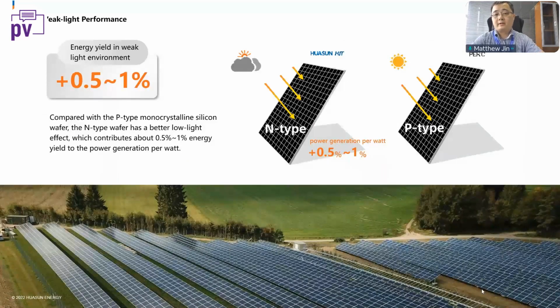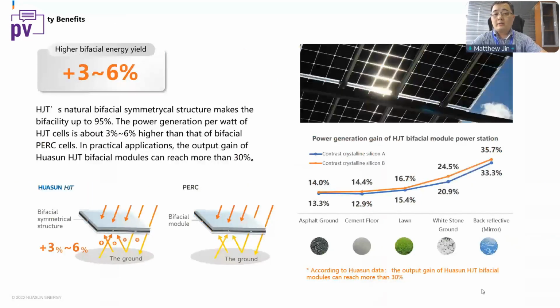For the great weak light performance, especially in the early morning and late in the afternoon, the weak light performance of the HJT compared with the P-type can generate more power, which can contribute about 0.5 to 1%. And the HJT has a better performance of bifaciality. Compared with the regular bifacial PERC, the HJT has up to around 95% bifaciality. But for the regular PERC panels, it's around 70 to 80%.